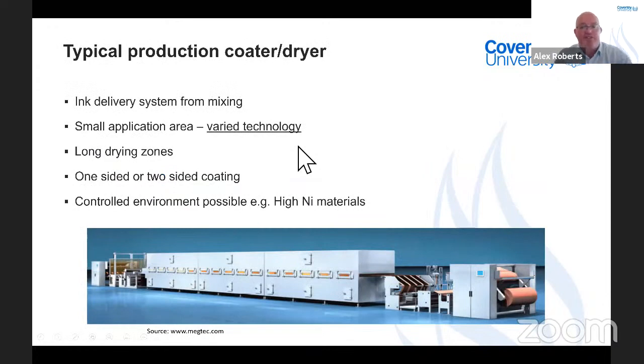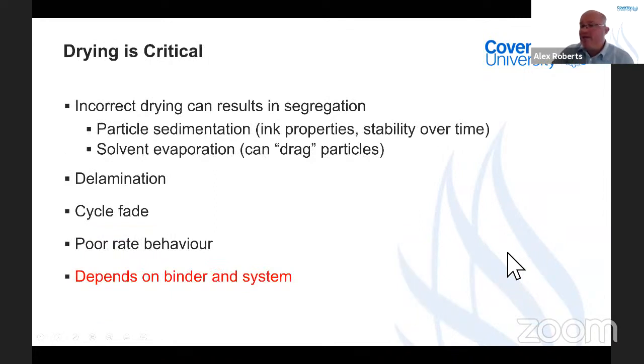So to look at a typical production type coater, I've taken this from the the Megtec website. You can see we would typically have a small ink application area, which you can see at the back side of the coater. Then you have a very, very large drying area. And these ovens can be over 50, maybe 100 meters long in some production processes. You've now got the technology available to be able to coat one or two sides at a time. And you can also put these under a controlled environment. And one of the big challenges that comes up is being able to run these coaters as quickly as possible. And for that, you either have a longer drying zone, or you may have a different type of drying or some completely new technology. So the drying is incredibly critical as you go through your process.